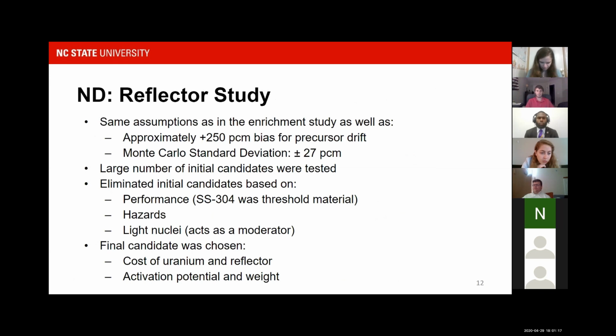We conducted a reflector study, which made the same assumptions as our enrichment study, but we accounted for the 250 pcm bias for precursor drift in this calculation and decreased the standard deviation by running more particles and cycles. We started off with a large number of initial candidates and then started eliminating them based upon the performance relative to SS304. If it performed worse than SS304, we eliminated it. If the material was considered hazardous, for example a powder that would be a lung irritant to the workers that would go in and repair the reactor, or if it contained light nuclei, which would act as a moderator, we eliminated it. We're a fast reactor, and so we would not want to moderate neutrons with our reflector.